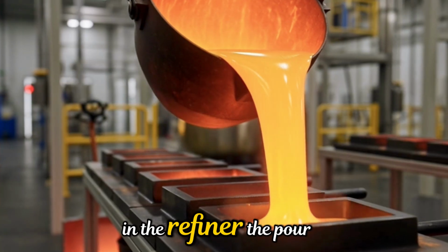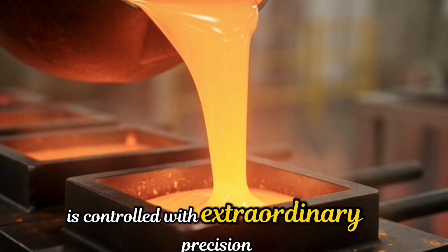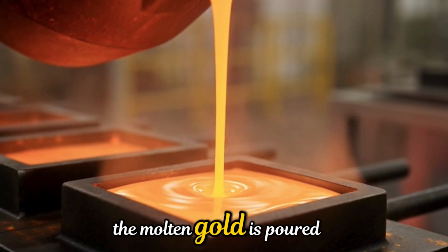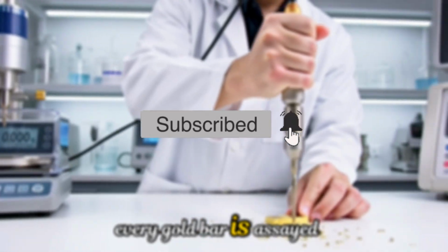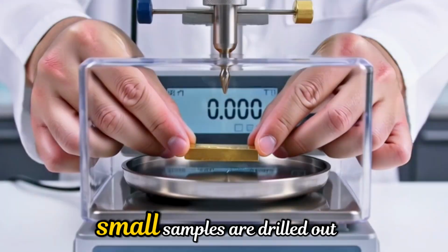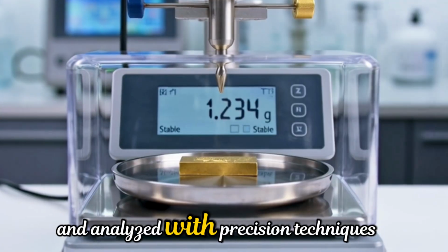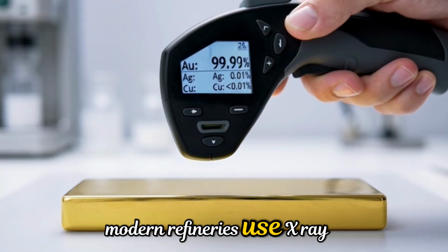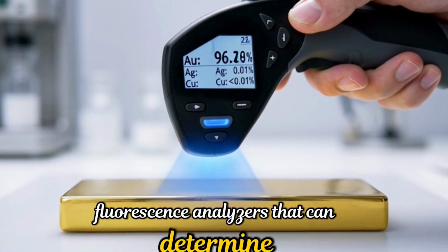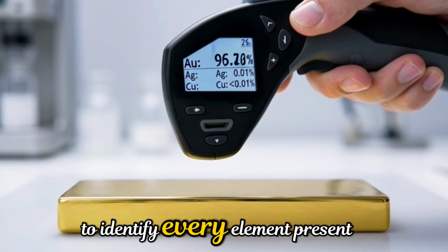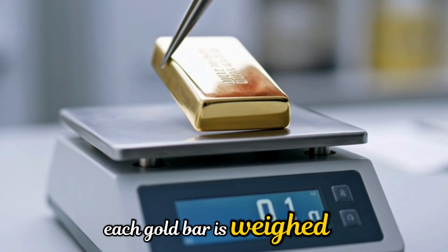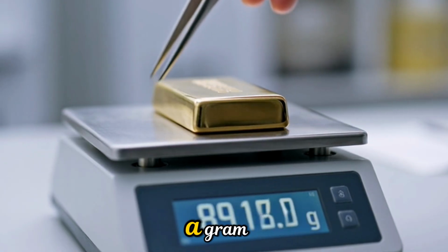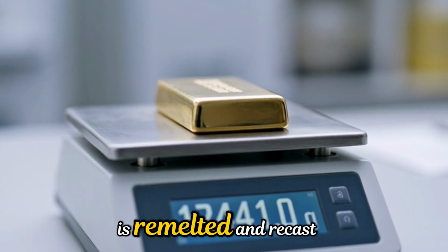In the refinery, the pour is controlled with extraordinary precision. The molten gold is poured into molds. Every gold bar is assayed, chemically tested for purity. Small samples are drilled out and analyzed with precision techniques. Modern refineries use X-ray fluorescence analyzers that can determine the exact composition to identify every element present. Each gold bar is weighed on precision scales accurate to 1/10 of a gram. Any deviation means the bar is remelted and recast.